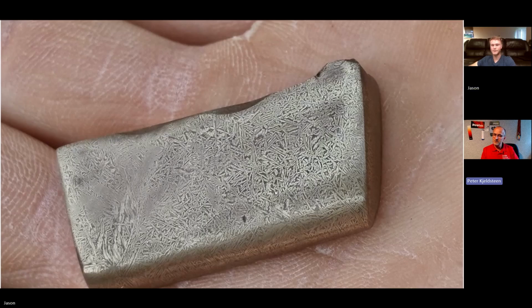When we go polishing, we go to microns. Then we talk about the grain size of the diamond particle, so it could be 3 micron or 1 micron you polish with. I'm not doing any diamond particles or colloidal silica at home, but just doing really fine sandpaper. And so I can take the etched surface and quickly pass over some very fine grit. I'm essentially polishing the elevated regions and not polishing the depressed regions. In other words, I'm applying a quick polish to just the alpha to really make it pop.